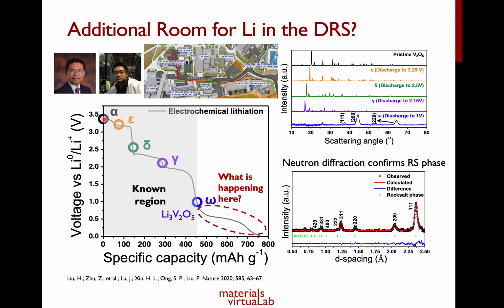So they took V2O5 and they tried to lithiate it. As they continued to lithiate it down to 1 volt, they essentially reproduced all the results that were reported by Delmas back in 1994. Okay, you see all these phase transitions from alpha to epsilon to delta, all the way down to the formation of your rock salt omega phase, right?